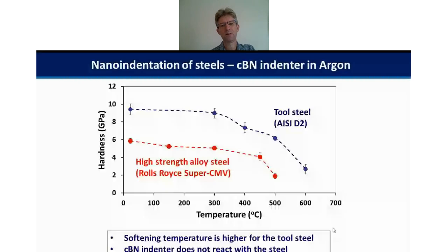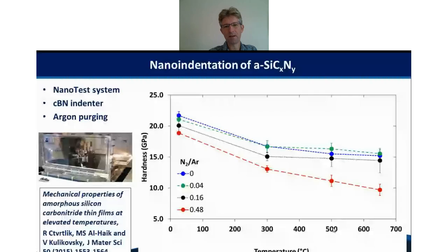So here, for example, we can contrast the high temperature properties of a high strength alloy steel developed by Rolls-Royce and the standard D2 tool steel, and we can see, for example, the softening temperatures change and the error bars remain low throughout that temperature range. So we don't have the same problems with the CBN indenter and steel as we do when we're testing steel with diamond. So the CBN is the preferred choice for steel.